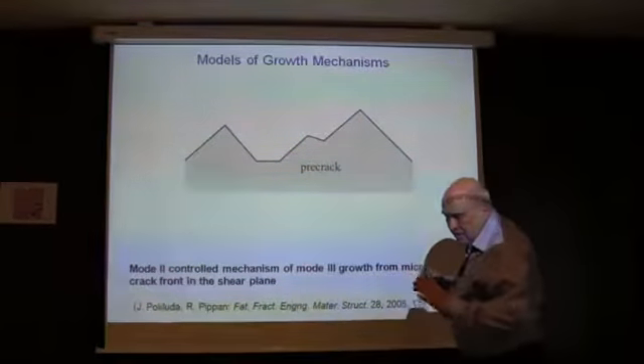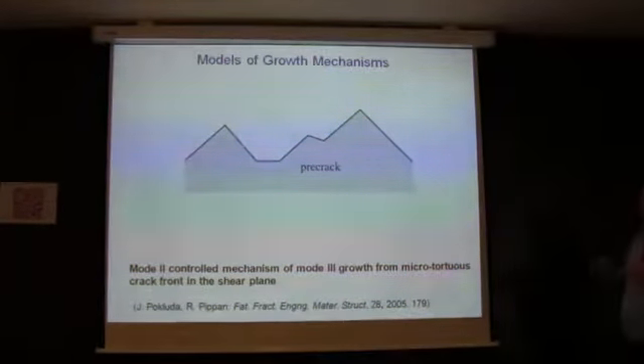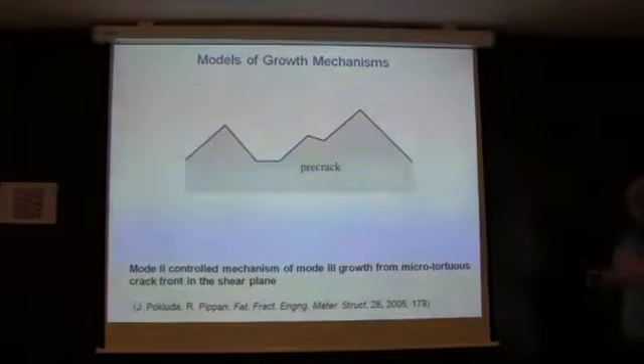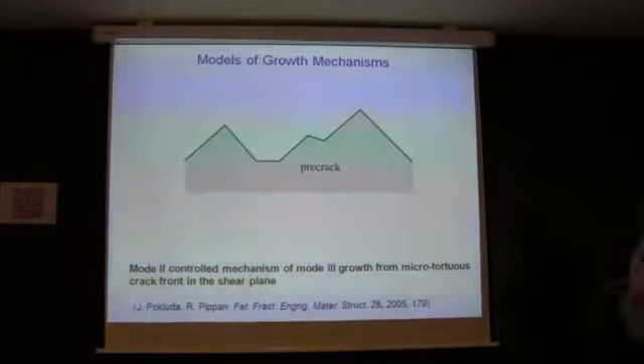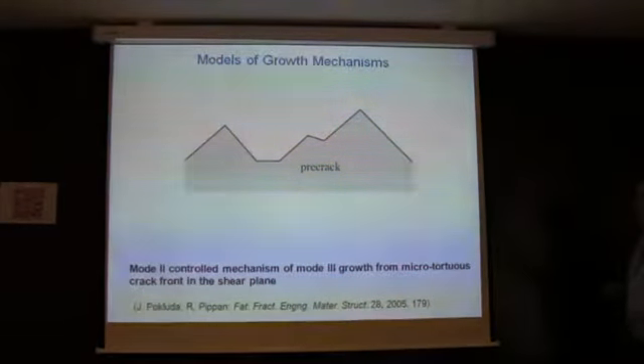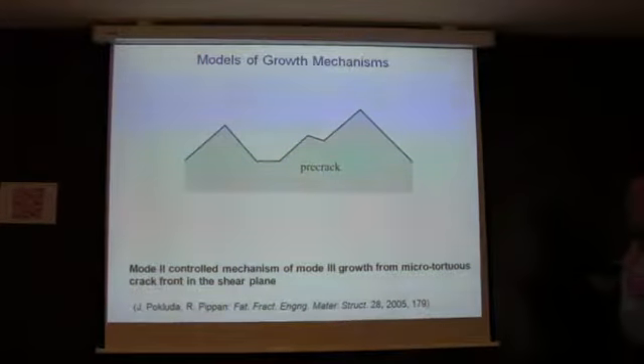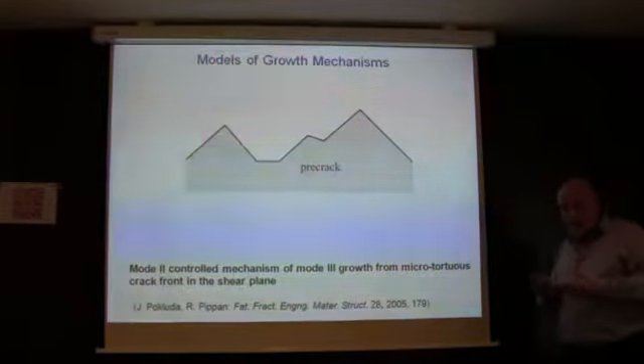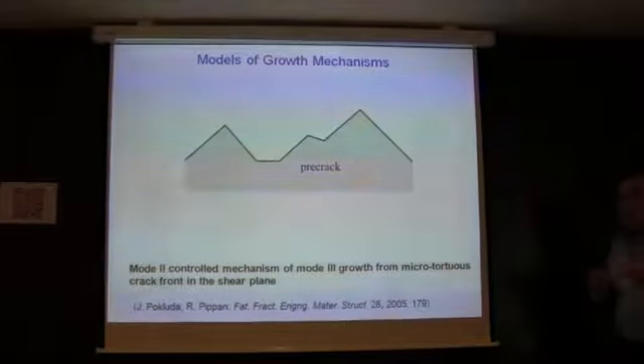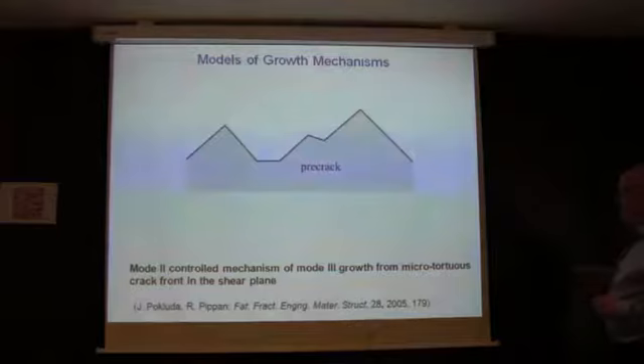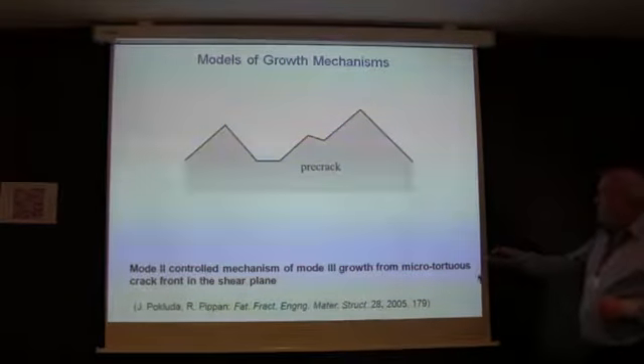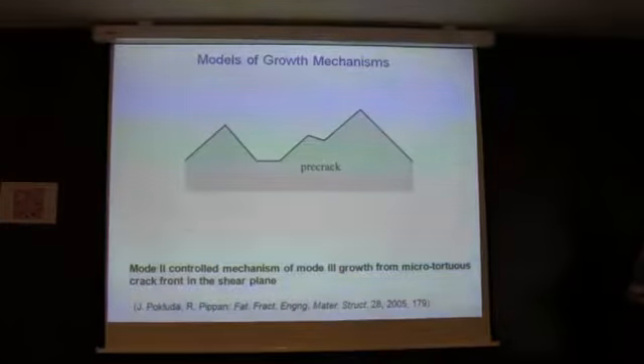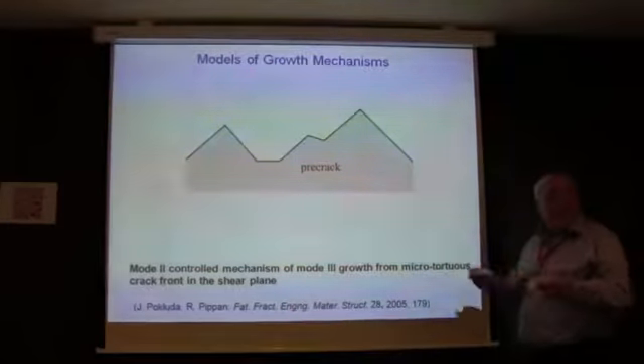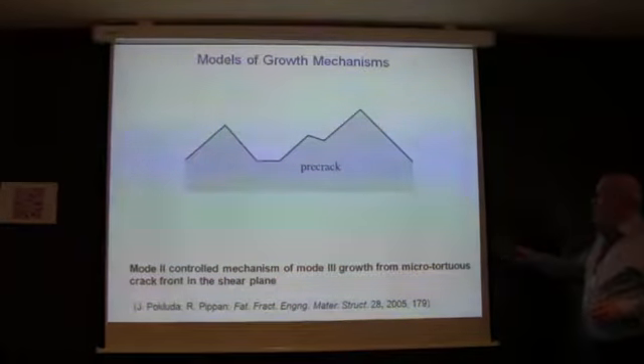So in summary, we can say that mode 2 should be faster than mode 3 for many reasons I showed you. So many years ago, we tried to explain how the crack in mode 3 can propagate just by mode 2 steps. Then you need a rough crack front like this, but this is always the case. The crack front in real matter is always microscopically rough.